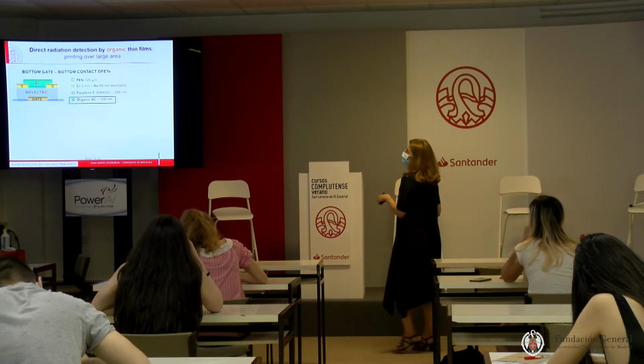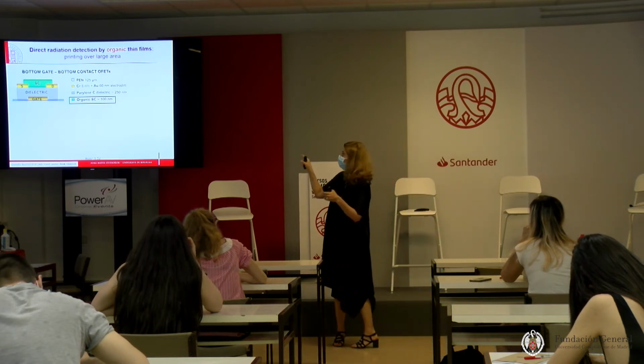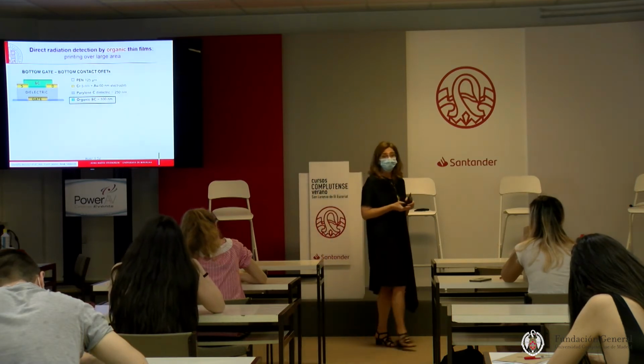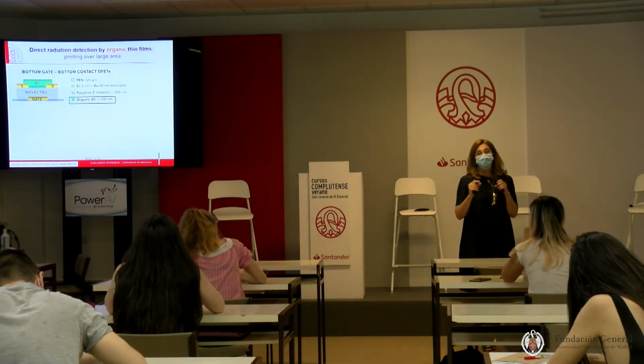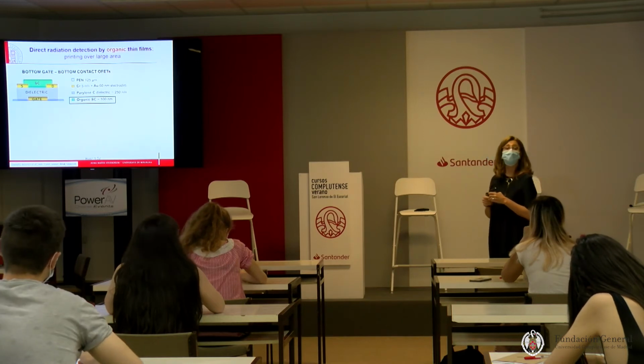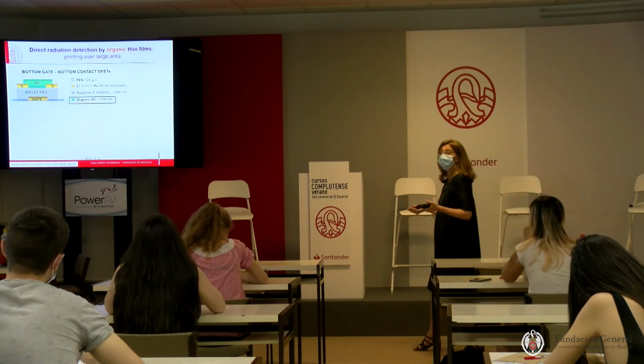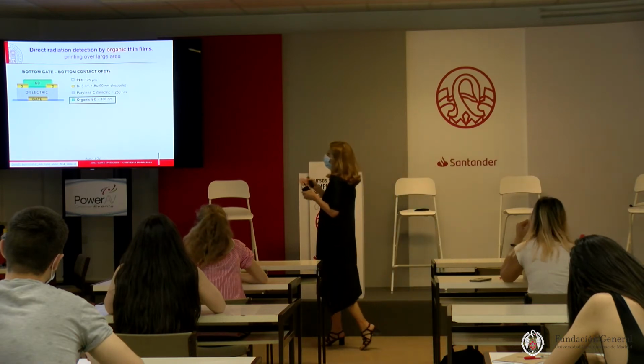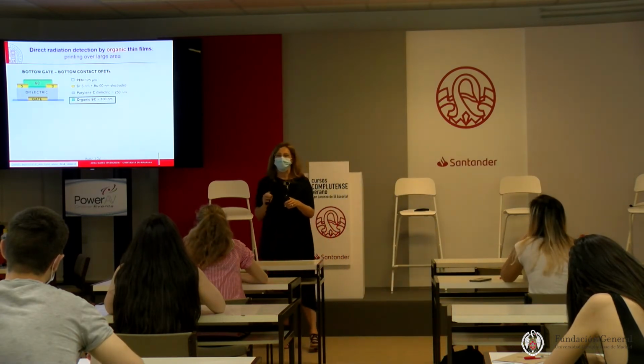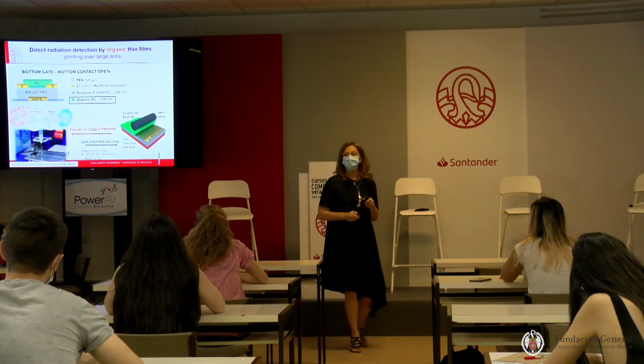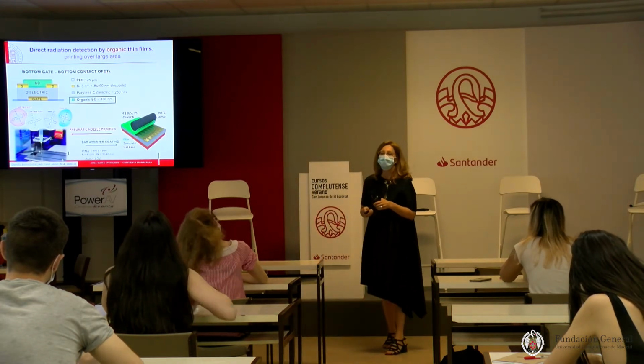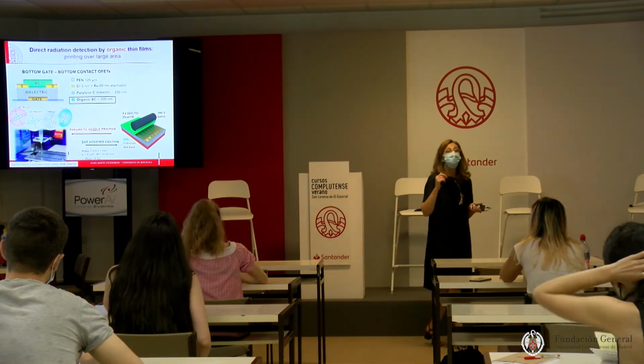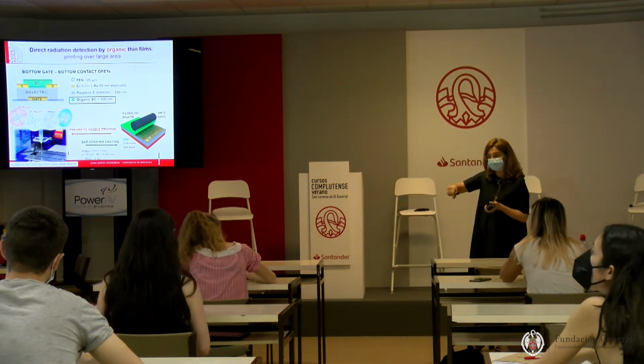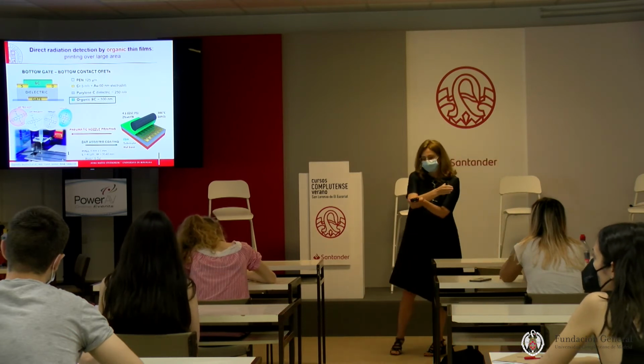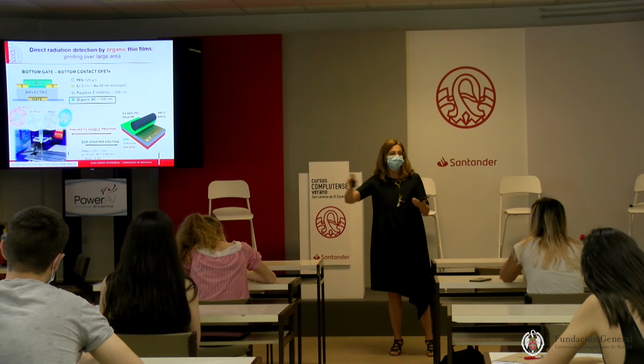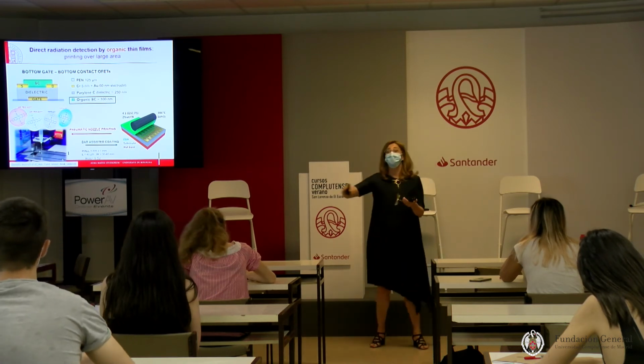Because if this is a typical structure, similar to the one I was showing you before, of an organic field effect transistor, the thickness of the organic semiconductor can be 100 nanometers to have it operate properly, even less actually. So we really use very little material, and we position it exactly where we need it. How do we deposit it? We use inkjet printing, nozzle printing, if we want to be more precise, or bar coating, which is using a bar to spread the liquid, the solution of the semiconductor, over a large area.